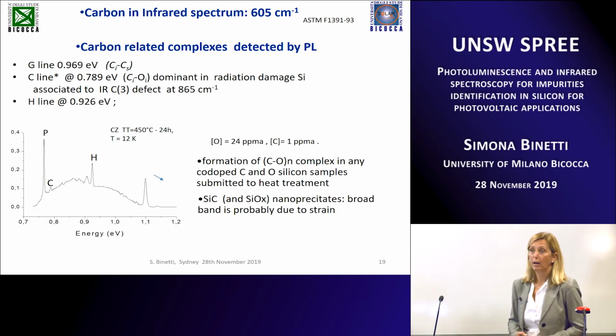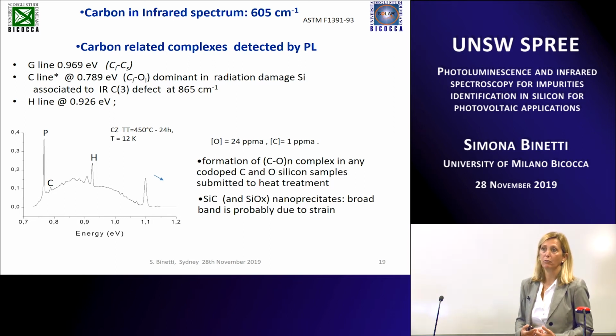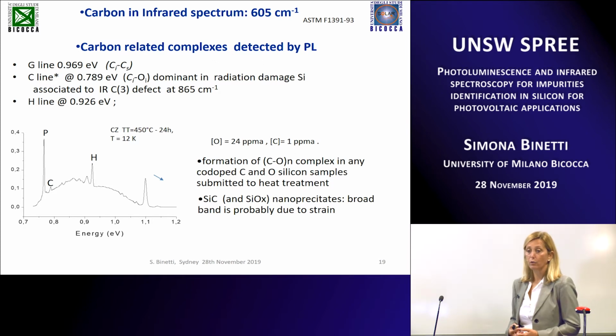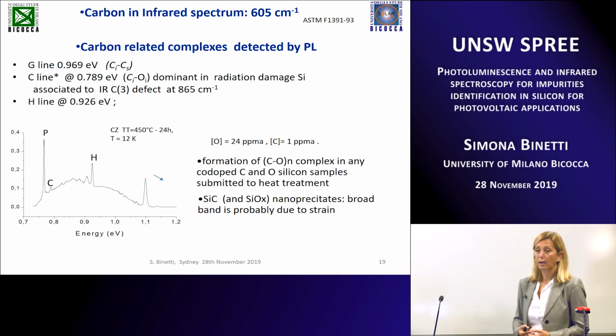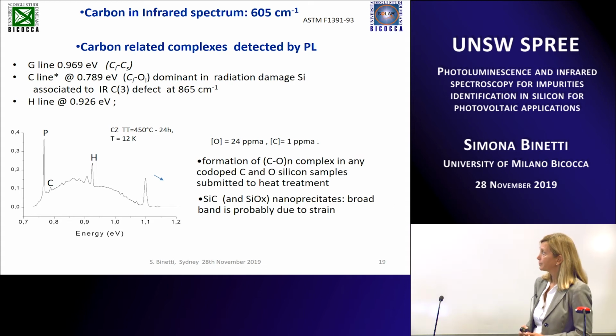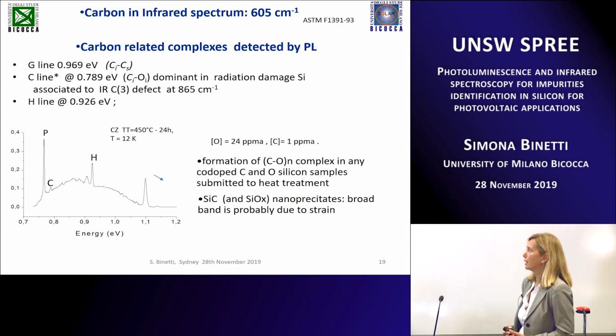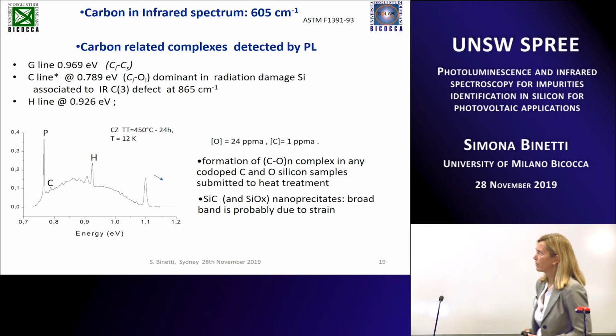Normally, these defects have been studied in radiation damaged silicon, in which you have a strong increase in the concentration of interstitial carbon and interstitial silicon, but they can be detected also in solar grade silicon. You can see, for instance, in this sample, which was not solar grade silicon, was a monocrystalline silicon with a very high concentration of oxygen and also carbon.